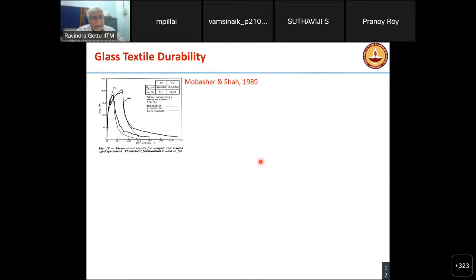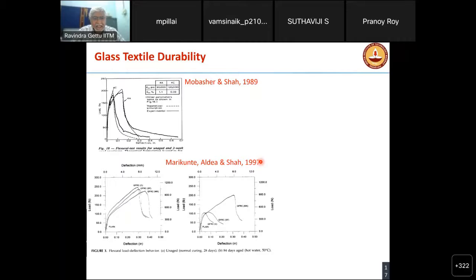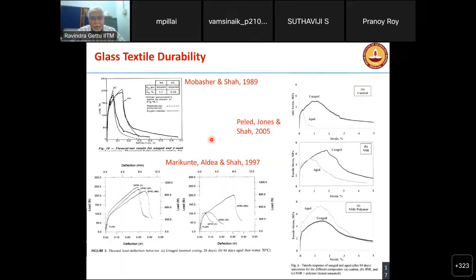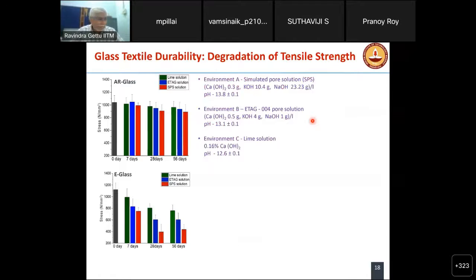More important is the glass textile durability. This has been studied from the 80s. This is work that I'm showing of Mobasher and Shah later, Professor Shah later in the 1990s, where they found that the textile can be attacked by the cement matrix. So we have been working a lot on this to see how to improve the durability. So again, due to aging of the textile within the concrete, there is a lot of loss in load carrying capacity. And this we can explain looking at this.